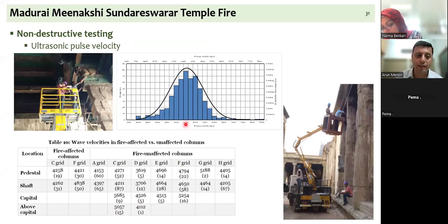We did some ultrasonic pulse velocity tests. The ultrasonic pulse velocity test gave us an idea that it was very surprising that the stone columns which were affected by fire and the stone columns not affected by fire did not show big difference in the velocity of the sonic waves. And that was a little counterintuitive. If you actually see the fire unaffected and the fire affected columns, the numbers, which are really the wave velocities, are not very different. So this was a little bit of a surprise for us.